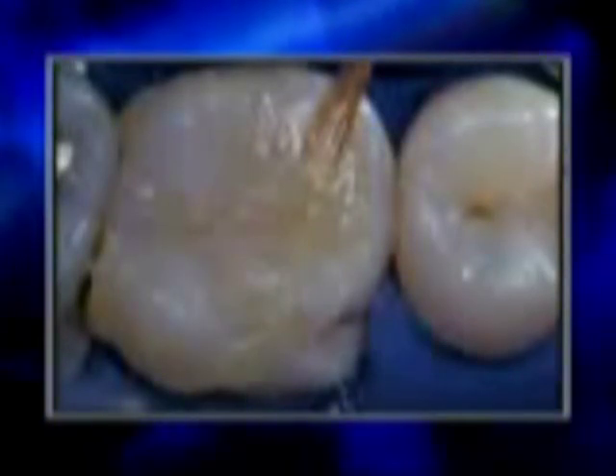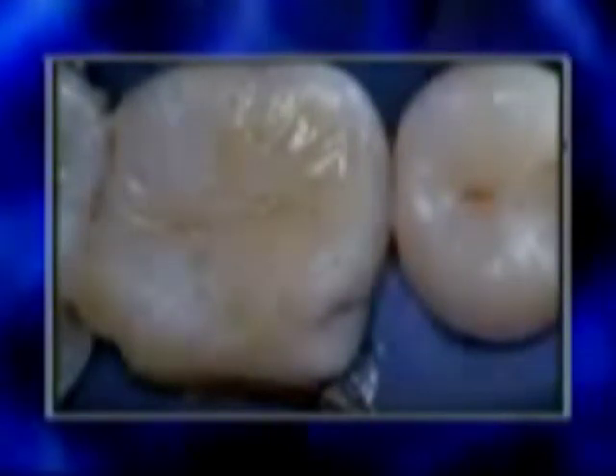The restoration was cemented with a yellow dual-cure composite resin cement, Nexus 2 by Kerr. The cement was mixed and loaded into a needle tube syringe tip and injected into the entire preparation. The onlay is gently seated into place. The excess cement is removed with a sable brush and the interproximal is flossed. It is imperative to leave a residual amount of cement to prevent voids and to compensate for the polymerization shrinkage of the cement. The restoration was polymerized from all aspects, facial, incisal, lingual, and proximal surfaces, for 60 seconds, respectively.